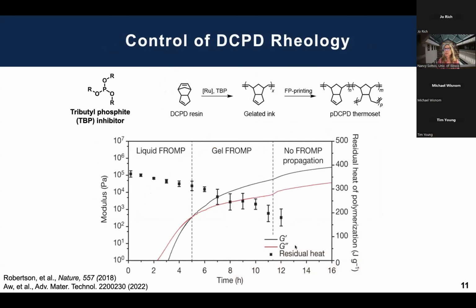And so what this means when we have the inhibitor with the DCPD is that there is a slow gelation stage, which can be quite useful for printing, or if we're infusing, we've got to do it before it gels. And we create the thermoset. And what you just see here is a plot of the storage modulus and the loss modulus as a function of time. It's a clear crossover point. Our crossover point fortuitously is very close to the actual gel point when the viscosity starts going up.